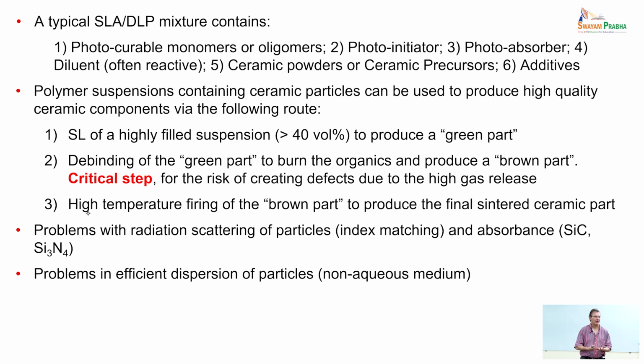And this requires, of course, a suitable thermal processing, which specifically means that you have to fire very, very slowly. And very slowly means that for a part this size, it takes 2 days, from putting the part into the furnace and taking the part out. And you're going only to 600 degrees Celsius. And people have found that debinding comes better if you do it in inert atmosphere, because the decomposition of the organics is not exothermal in that case. If you burn out in oxygen, you have oxidative exothermal reactions that can lead to localized cracking.